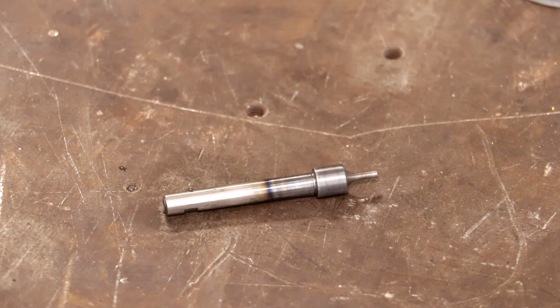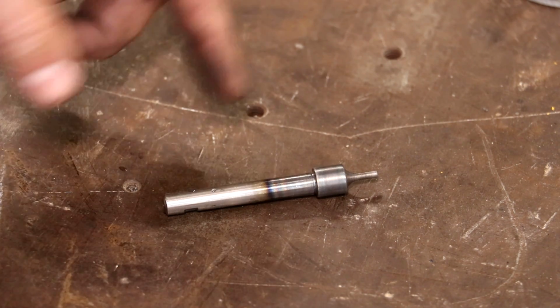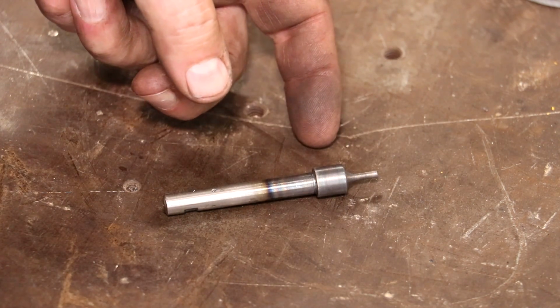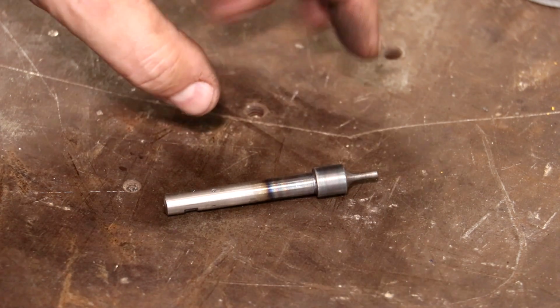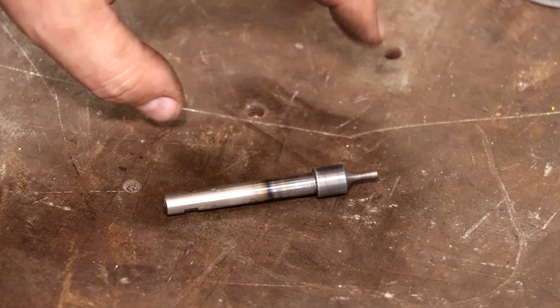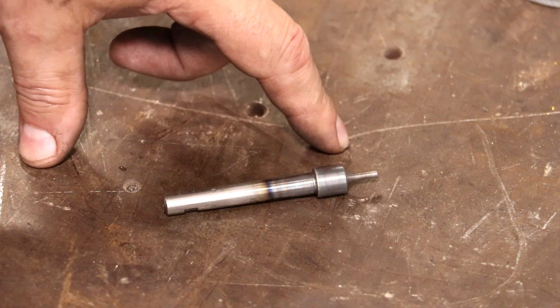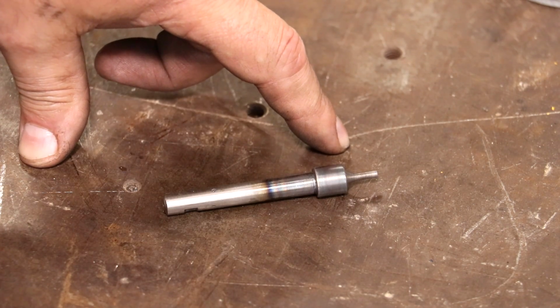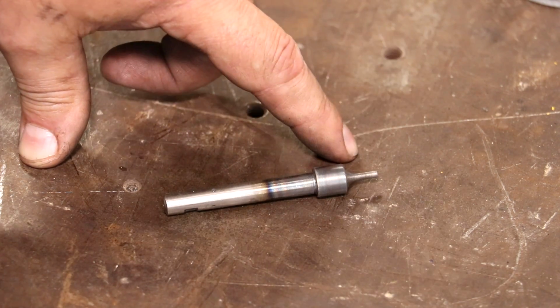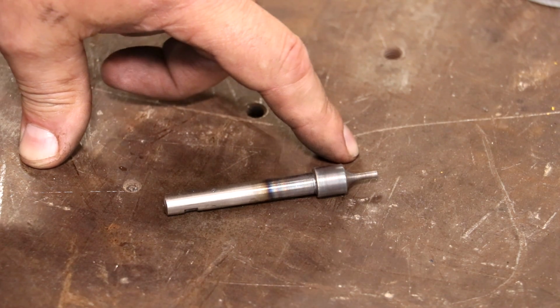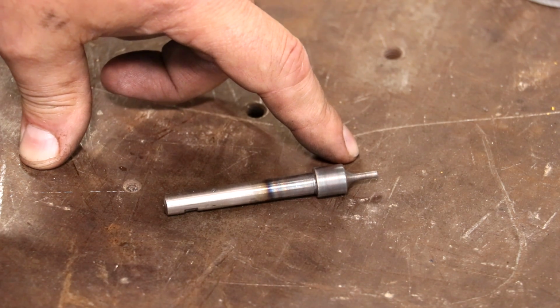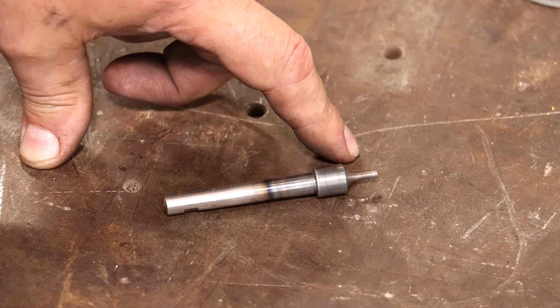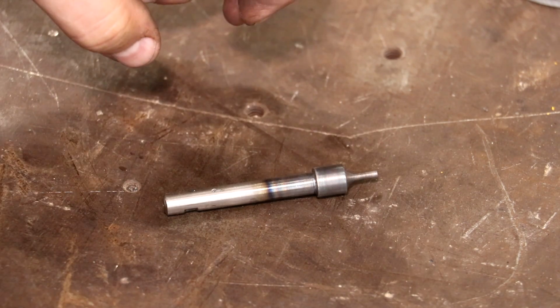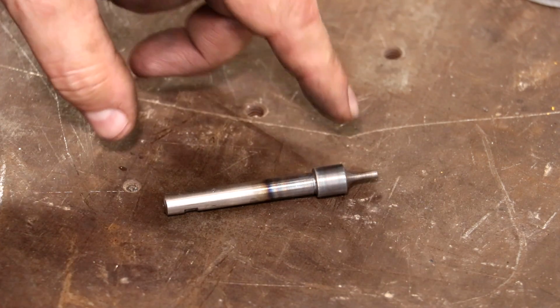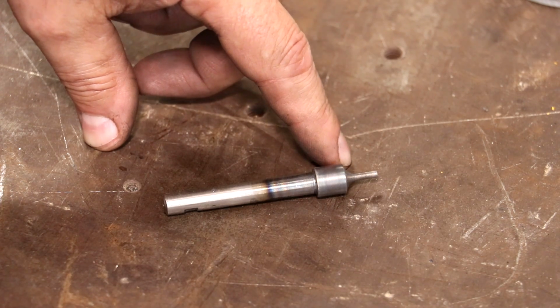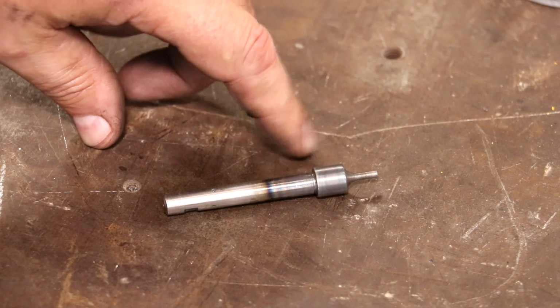According to the book, it should be at about Rockwell 60. I want to get this down to about Rockwell 50, maybe even a little bit lower than 50, probably 47 to 50, somewhere in that ballpark. And according to the book, after doing what I just did, if I heat this up to, I need to double check, it's either 500 or 600 degrees, hold it there for 2 hours and let it cool down. It will draw that temper out, or draw that hardness out, and make it a little bit softer. Still hard, but not as hard as it is right now.